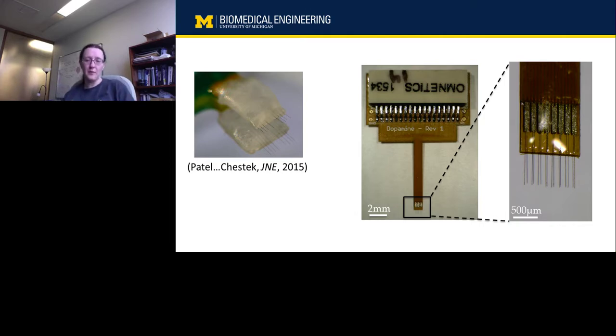Another device that we do a lot of work with is pictured on the right. That's kind of our workhorse device, where we just have carbon fibers projecting off the end of the circuit board. And we can actually put that in a cannula. So that lets us get anywhere in the rodent brain, where the cannula is obviously going to do some damage. But the carbon fiber extends 500 microns past that. And so, typically that's enough to get outside of the damage radius of the cannula. And a lot of the early results we've seen in recording from neurons came from these workhorse devices.